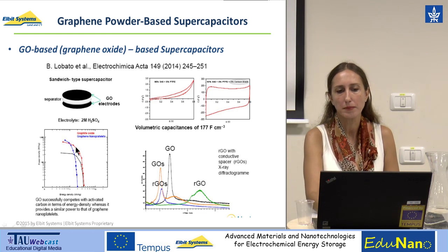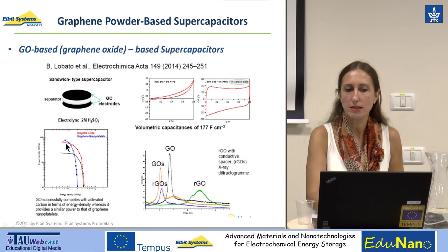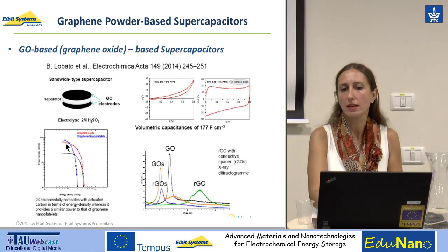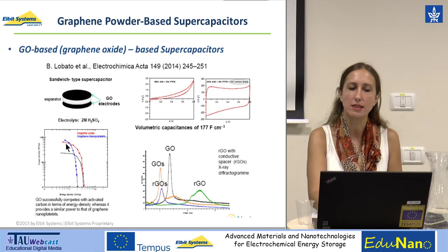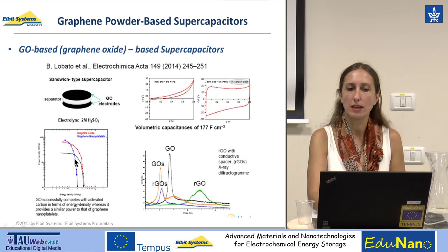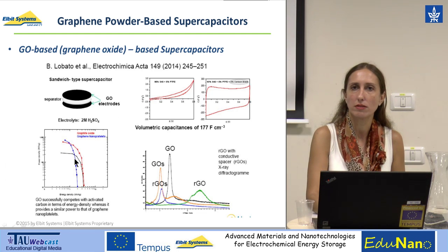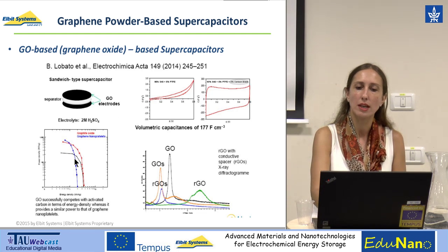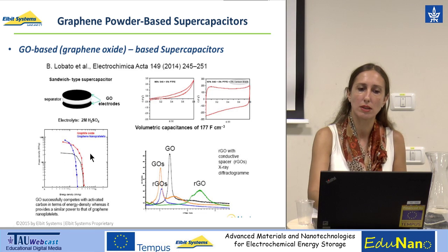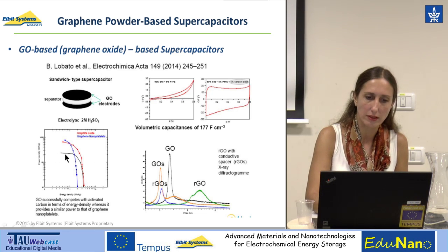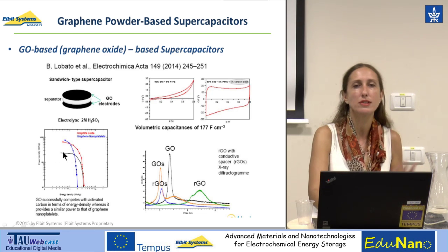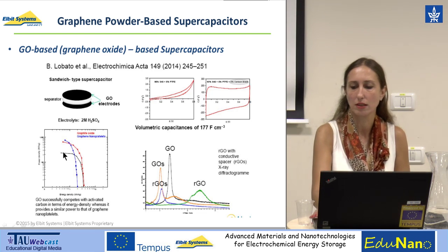So this shows experimental evidence that using reduced graphene oxide one can actually substitute the activated carbon powder and attain higher energy values. And we are talking about a difference of almost an order of magnitude. It is a huge improvement.